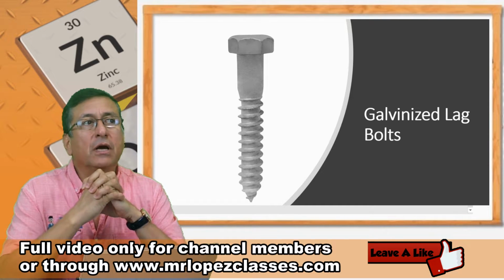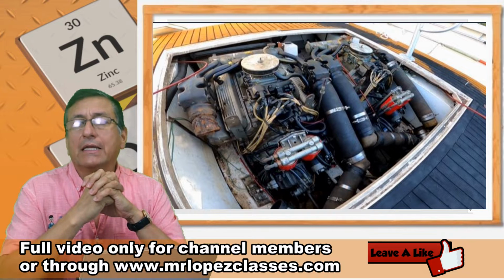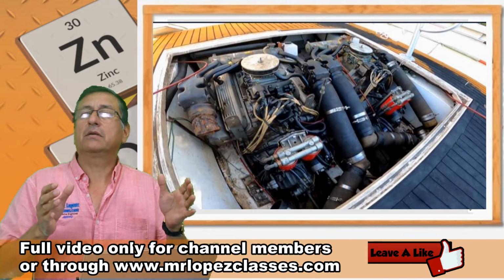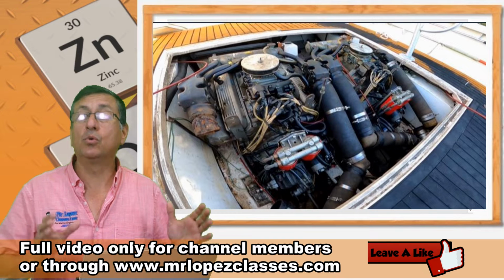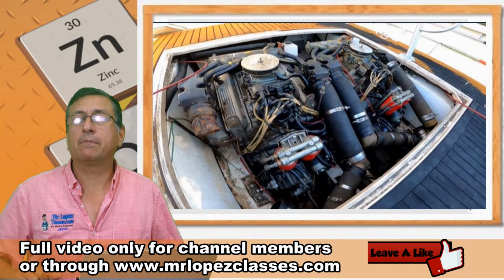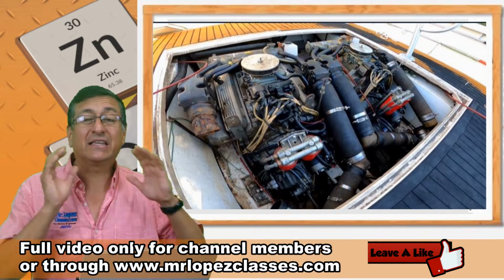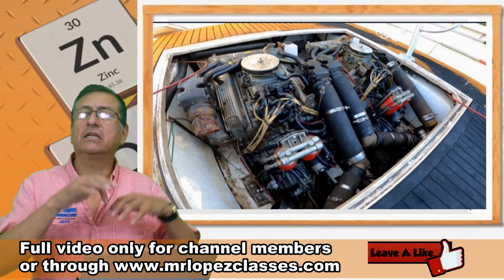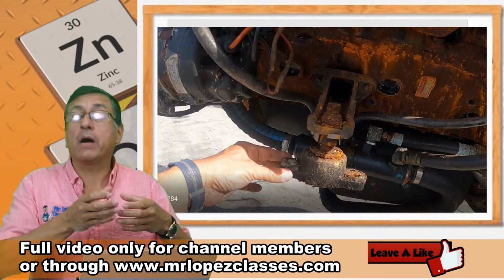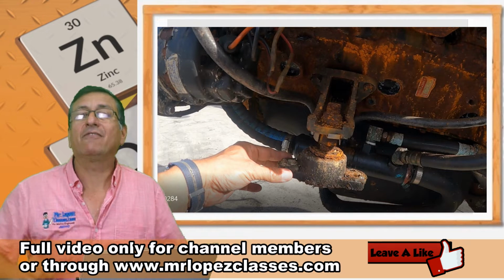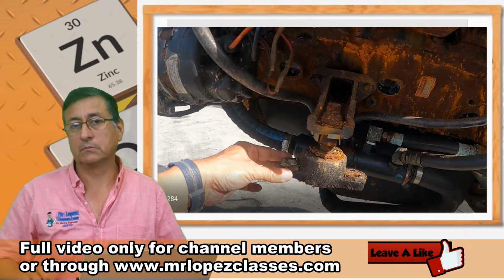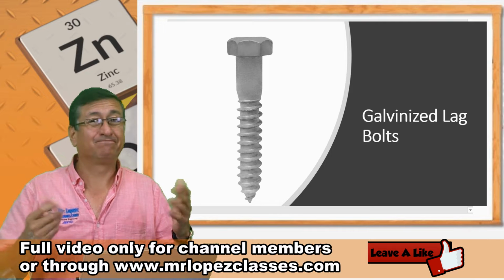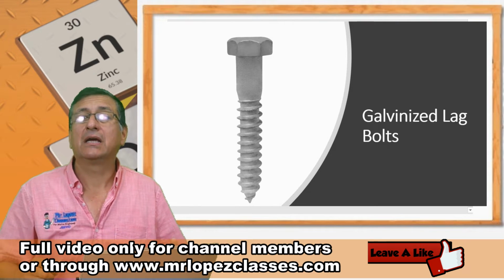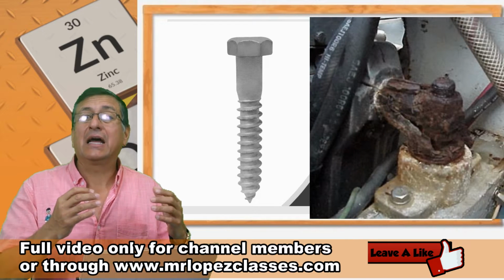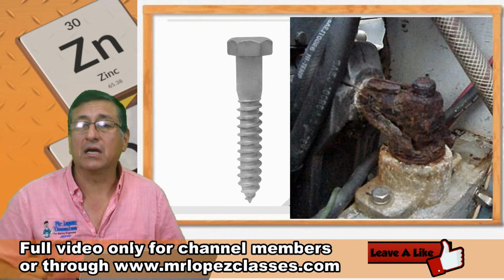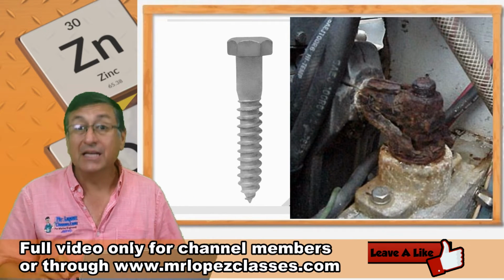With Mr. Rodriguez, we received an inboard boat with 2 Mercruisers, and the stringers were deteriorated because water penetrated the stringers, because the motor mounts were installed with galvanized lag bolts. The galvanized bolts corroded and corroded the fiberglass, and the humidity entered into the stringers and destroyed them.